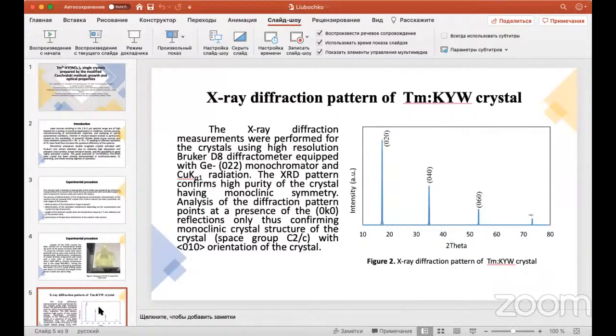X-ray diffraction patterns of TM:KYW crystals. The X-ray diffraction measurements were performed for the crystals using a high resolution Bruker D8 diffractometer equipped with the germanium 022 monochromators and copper K alpha 1 radiation. The X-ray patterns confirmed the high purity of the crystals, which had monoclinic symmetry. Analysis of the diffraction patterns points at the presence of the 0k0 reflections only, thus confirming the monoclinic crystal structure of the crystals with 010 orientation of the crystal.